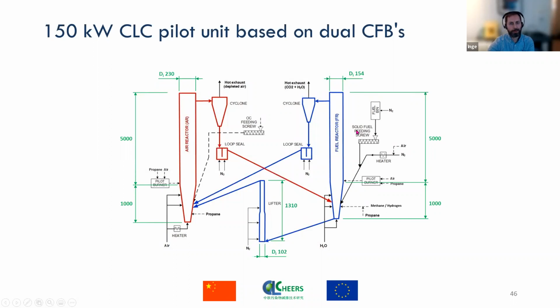Yeah, the fuel reactor is quite small, designed for quite high velocity and high particle transport. So the residence time is quite low in the fuel reactor. And we don't have a carbon stripper in the system. So that means that this system works best for reactive fuels, because there is quite low residence time for the gasification to take place. Yes, we also run this in autothermal operation, so we cannot really set the temperature. You have to use the process to adjust to the right temperature. The only heating we have is the electric heater to the primary air to the air reactor.